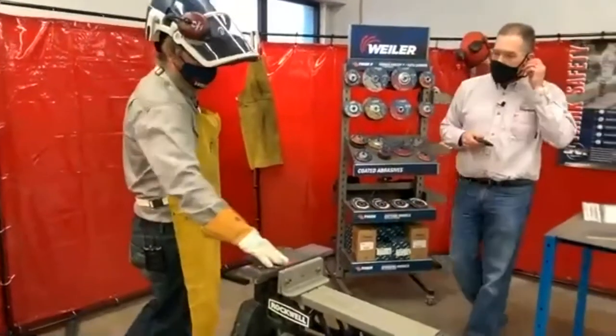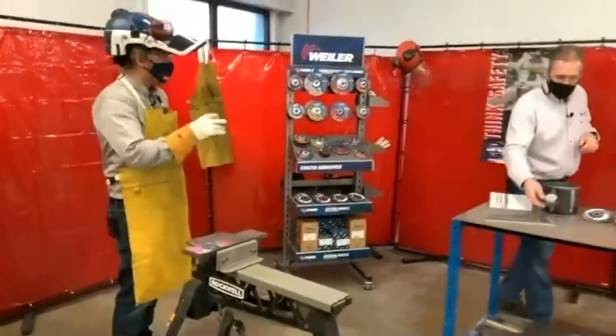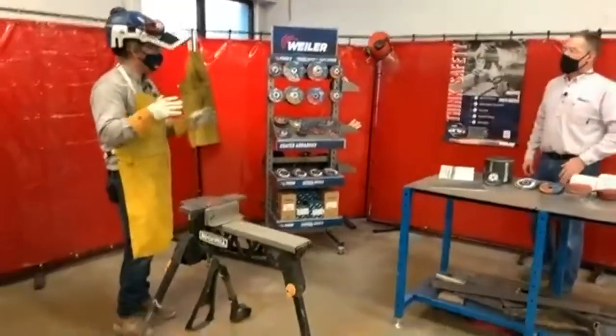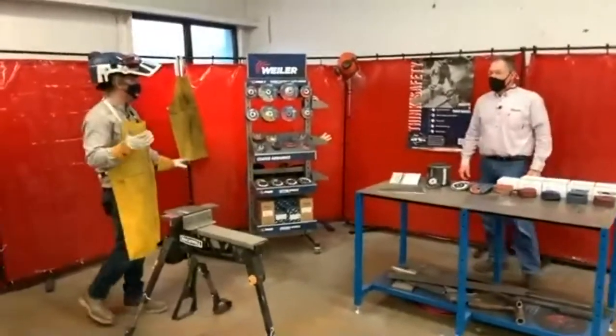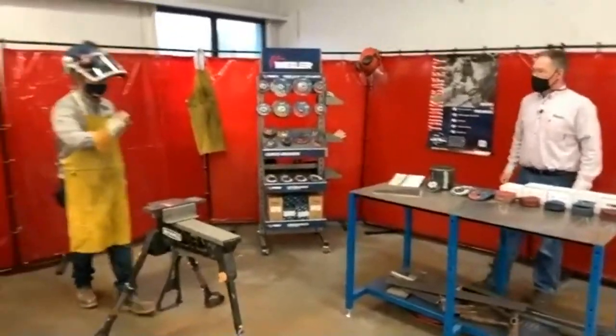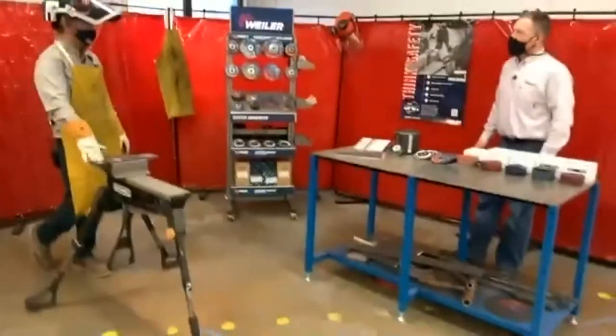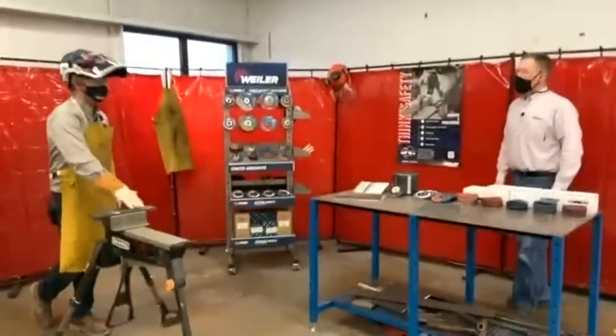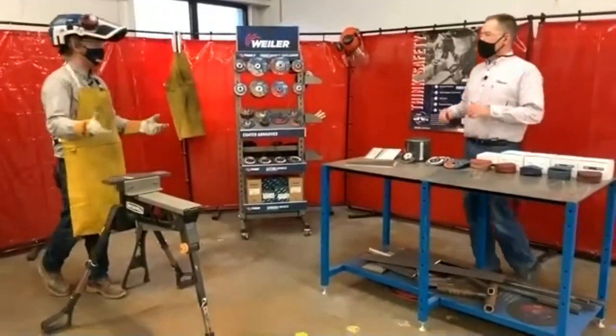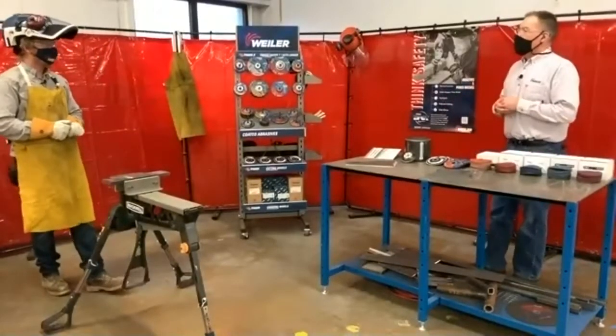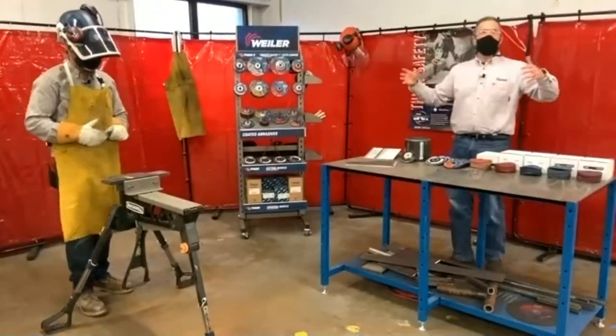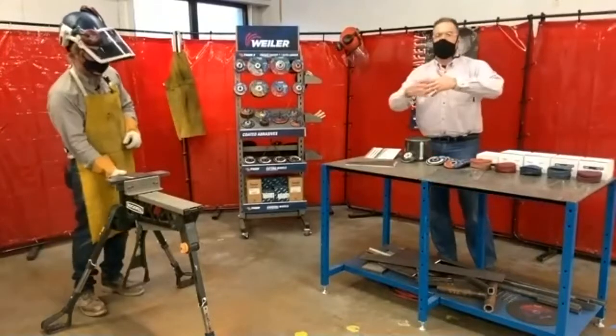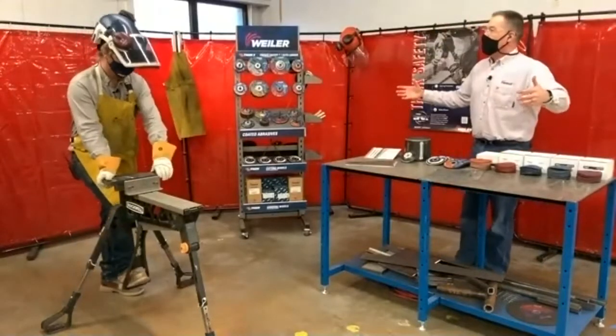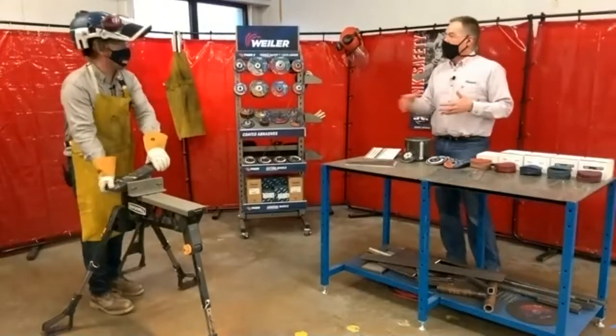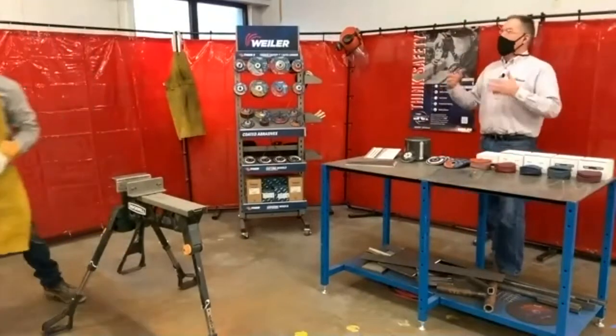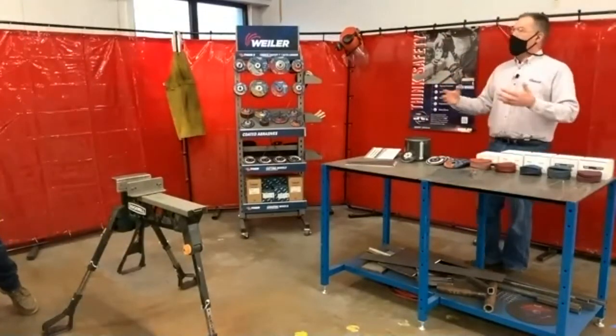Right. And my first full pass here with the resin fiber disc, I felt I was removing at least 3/4 of an inch to 1/2 inch of mill scale just on that first pull, when our flap disc barely removed any on that first pull. Our bonded abrasive did a great job removing it, but that's a secondary process to clean it back up. So again, we're not saying that resin fiber discs are the end all and be all, or any one of these abrasives. But there are benefits and there are also compromises with any product that you choose.